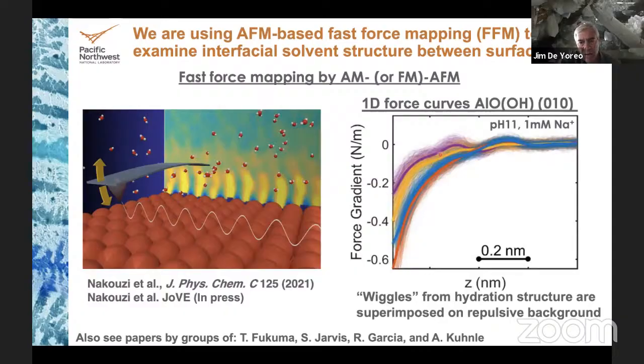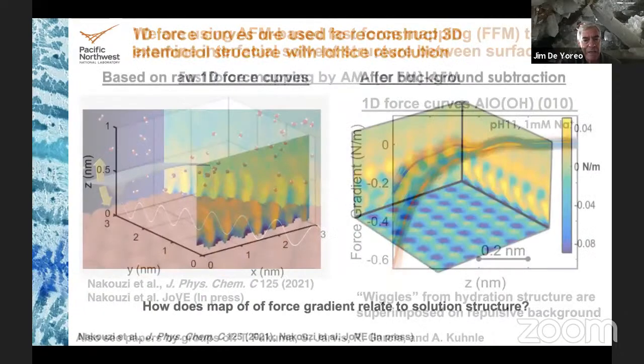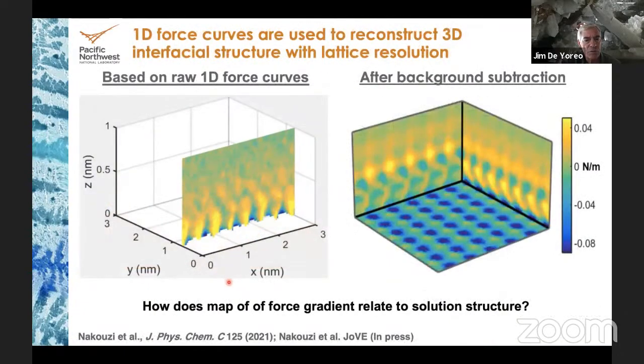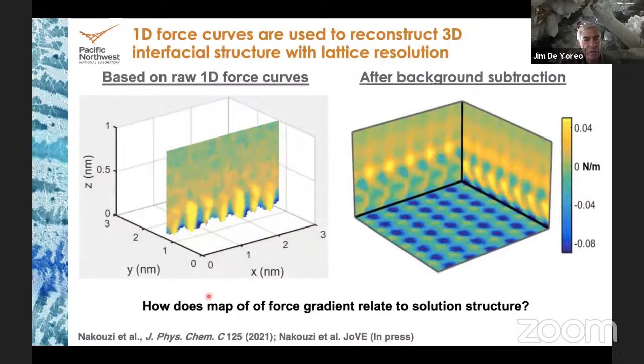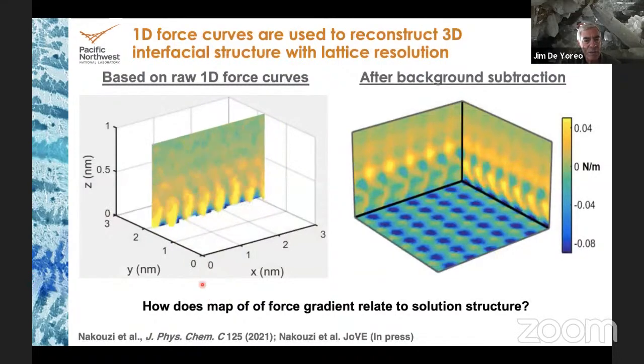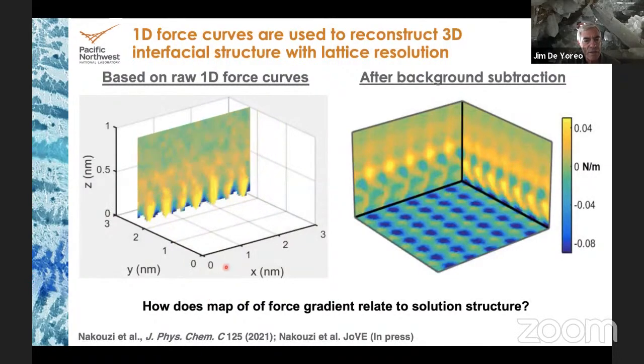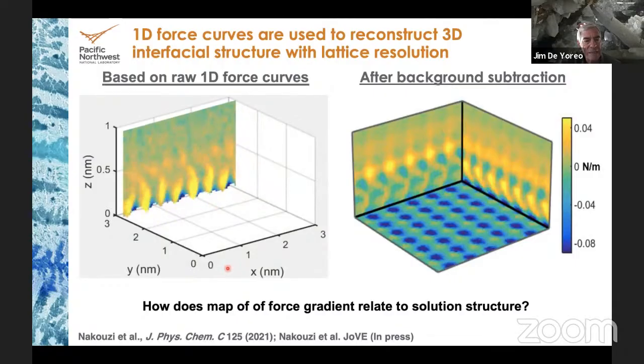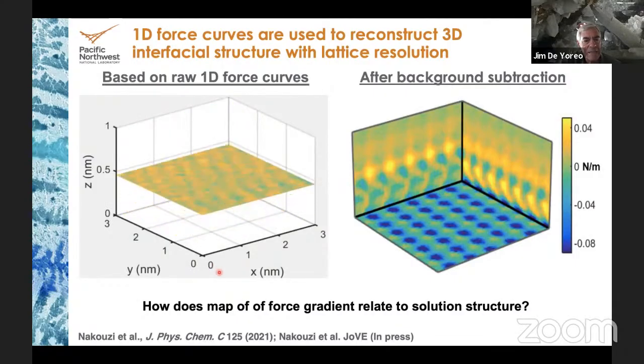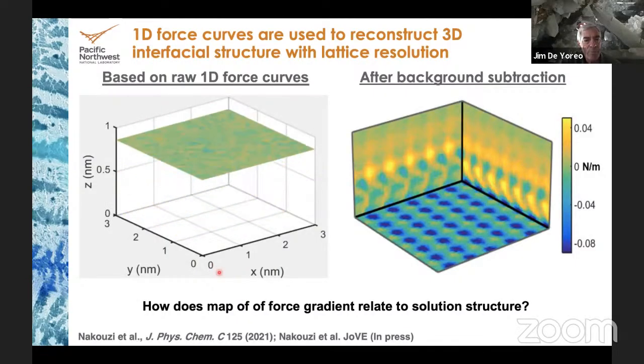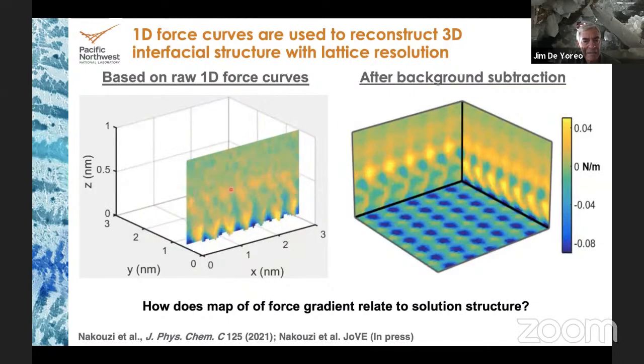Now, if we take all of those curves, we can reconstruct a three-dimensional plot of the solution above the surface. And that's what you see here. You're looking at a vertical cut right now as we go across the surface. The bright areas are low density, the dark areas are high density. And now we're up in the bulk. And this has the background in it.